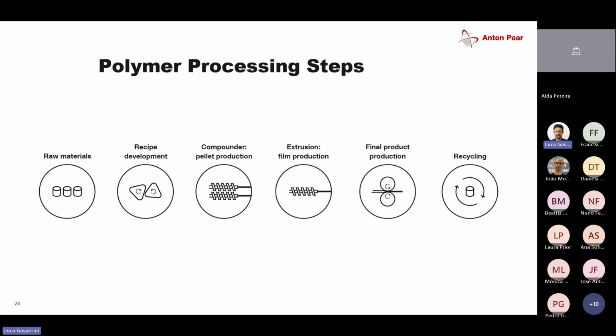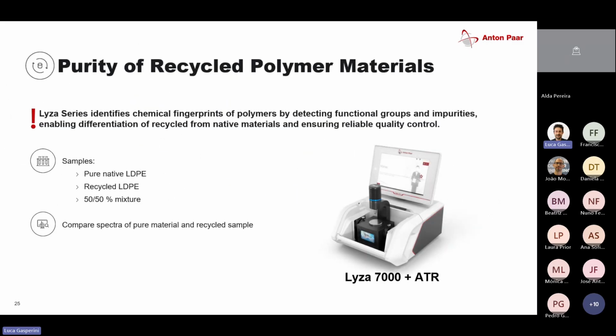Which brings me to my last example. So now we are done with all of this, so we start with the recycling. How can you use FTIR for recycling purposes? What we did is we had 3 different samples: one pure virgin LDPE and then recycled LDPE. How did we recycle the LDPE? We just threw it into the extruder 5 times, and we did some mechanical recycling. And then we also produced mixtures, so 50% virgin, 50% recycled.